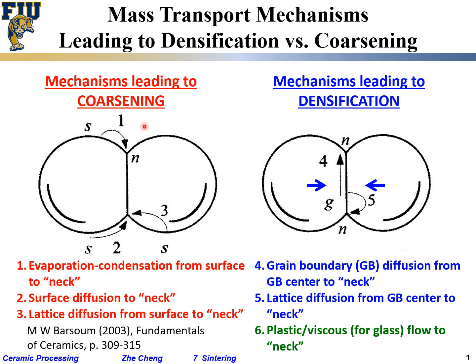On the other hand, if the material has a high tendency to evaporate, it doesn't densify as much. The material would quickly eliminate the sharp protrusions but the center-to-center distance from particle to particle does not change — it remains the same — except those curved surfaces now become more flat.